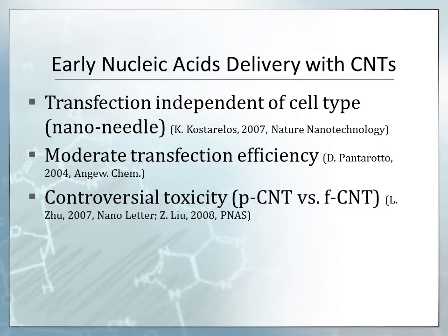So, can we use CNTs to deliver nucleic acid? Very interestingly, yes. In 2004, Pantarotto used CNTs for delivering plasmid DNA encoding GFP, and surprisingly, some of the cells exhibited green fluorescence. Later on, researchers found out CNTs can get into the cells independent of cell type to a similar degree, which is diffusion-like. It's another surprise because it's known that quite a lot of cells are difficult to transfect. And another notable thing is it has a controversial toxicity, basically because it depends on how the CNTs were functionalized.